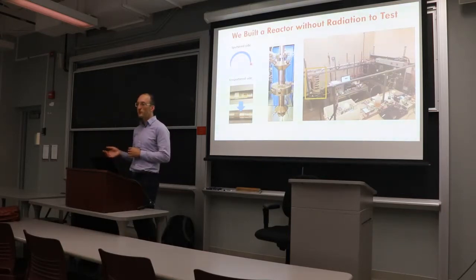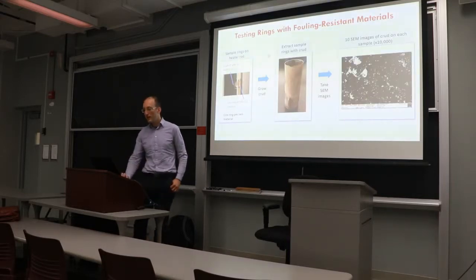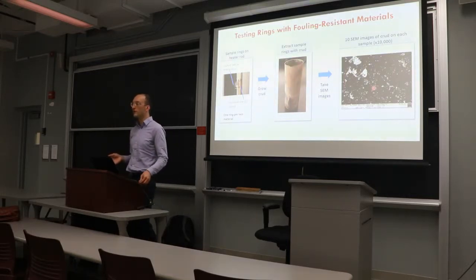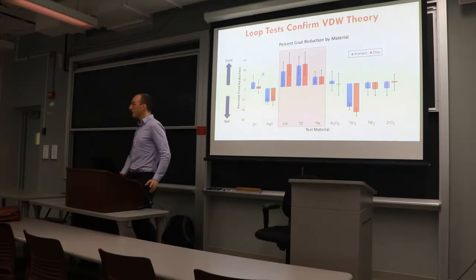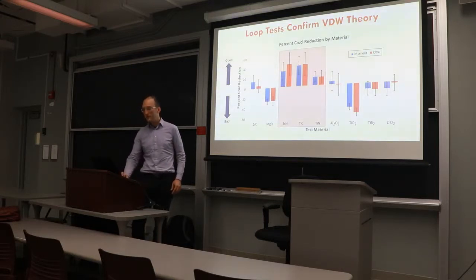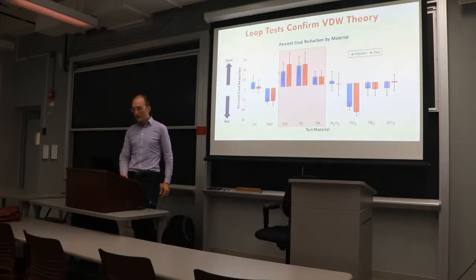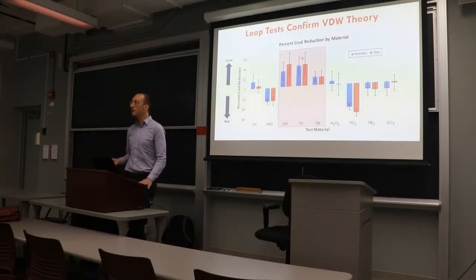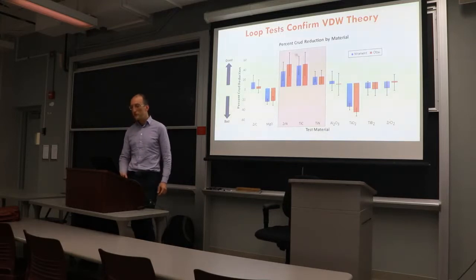So if there's any mismatch between thermal fit or slight dimensional tolerance between these rings and the heater, we account for that. We then take those rings off the experiment, which get pretty cruddy, take SEM images and look at how much of the surface is covered in crud. And then we plot that as a function of material and as a function of some various other image processing parameters. And we end up with a graph like this. The way to read this is up is good and down is bad, and the x-axis is just different materials. So the materials that show a positive crud reduction actually reduce the amount of crud deposition repeatedly at PWR conditions. And these are 2 sigma error bars.